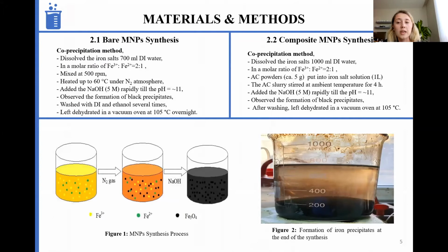Well, the synthesis of each magnetic nanoparticle was conducted with the co-precipitation method. Both of the synthesis procedures are similar, and mainly the used iron salts were in a molar ratio of 2:1 in each synthesis procedure to provide magnetic nanoparticle precipitates. High pH was adjusted for each synthesis procedure again. As you see in figure 2, it shows the formation of the iron precipitates at the end of the synthesis. And at last, they were washed out and lastly left dehydrated.